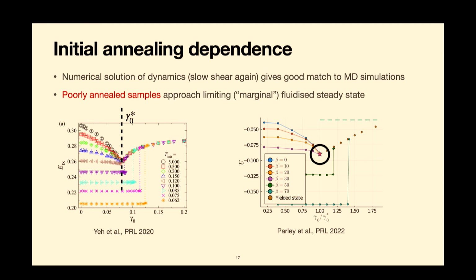There is a characteristic strain where all of these curves meet and they all have the same energy there. So that's sort of the limiting frozen state in some sense. All of these samples are still frozen in the sense that they behave elastically in steady state, and then beyond that point we have the fluidized states, where the energy is a unique function of the strain. So you see this is a very good qualitative match between the theory and what happens in the simulations, even though the theory is relatively simple, it's only a mean field model that ignores a lot of spatial structure. So that was the poorly annealed samples.